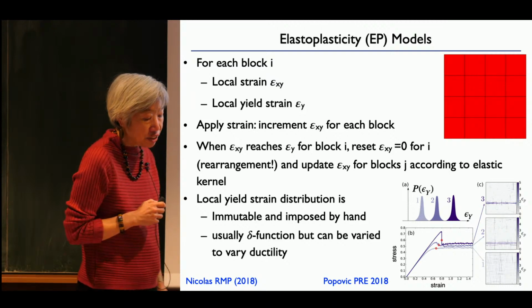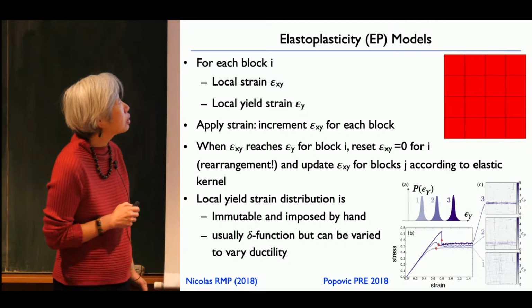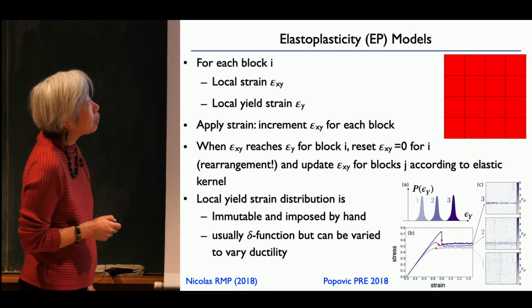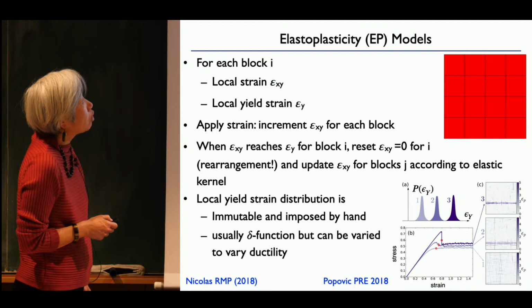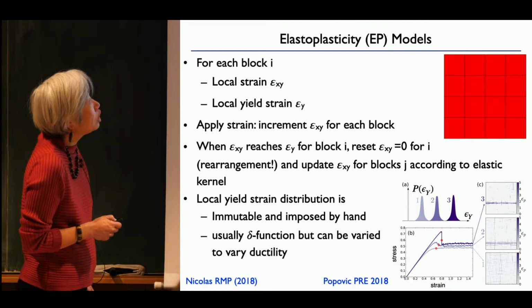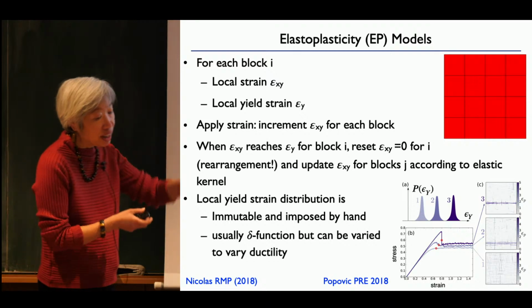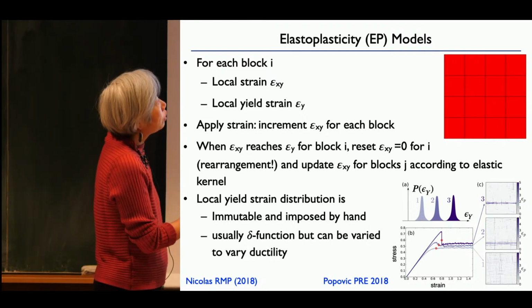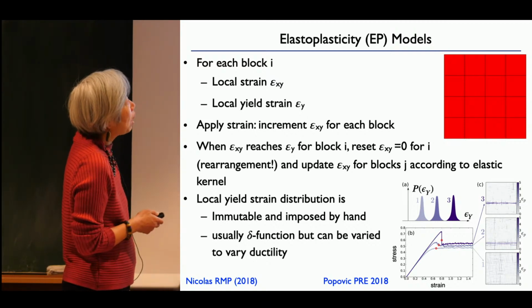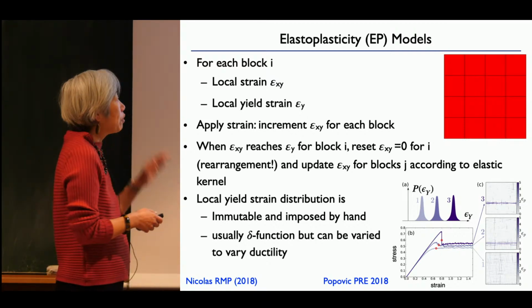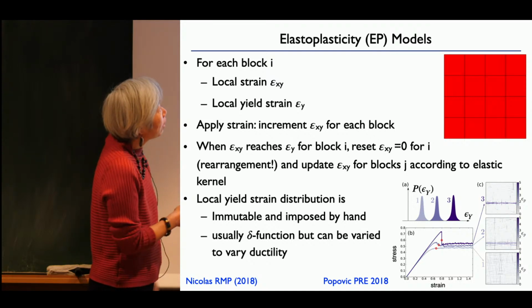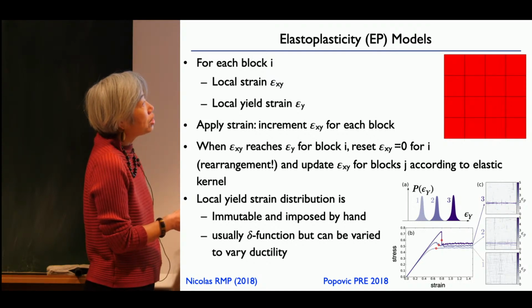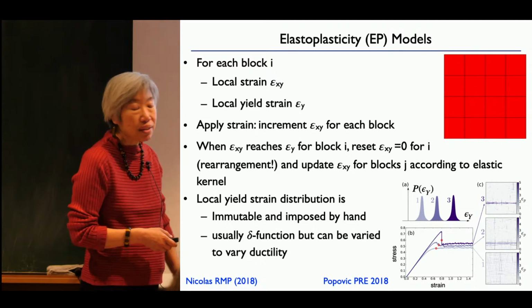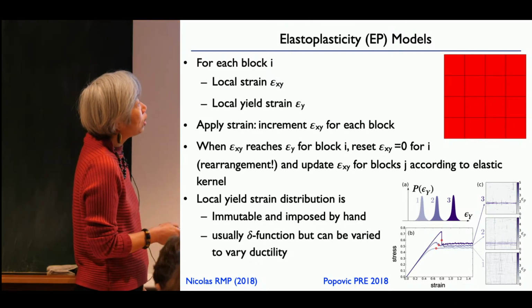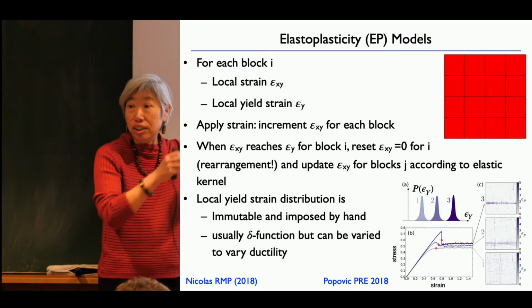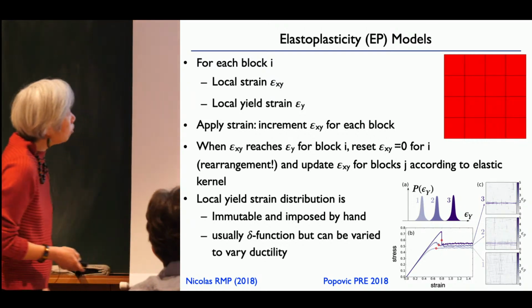All right. So let me just first say a word about ordinary elastoplasticity models. What you do is you have a system of blocks, and on each block, you put a local strain, epsilon xy, and a local yield strain. And then you apply the strain. You just add some increment to the xy strain on each block. And then when the strain on a given block reaches the yield strain, you reset the strain to 0 for that block. You say there's been a rearrangement, you record that, and you update the strain on the other blocks according to that elastic kernel, the strain that it exerts on all the others.